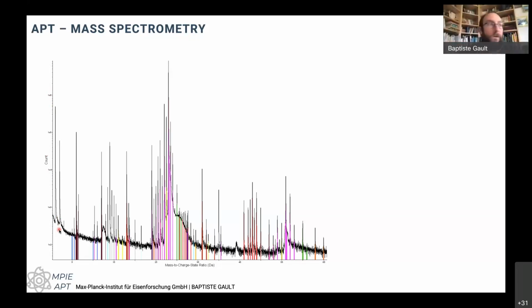So there's been quite a lot of work done on carbides in steel that are used to trap hydrogen, or some highly deformed cementite particles in pearlite, for example, that tend to trap a lot of hydrogen as well, whether it's trapped at the interface or inside of the particles. So this has been done quite a lot. The second point is that the hydrogen that we can see this way is typically hydrogen that is trapped. It's not hydrogen that is mobile through the matrix. And that goes to the second point. Is it going to stay in the specimen when the specimen is so small?